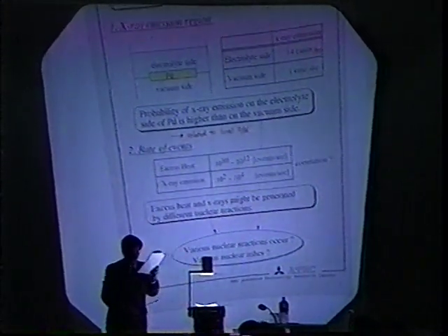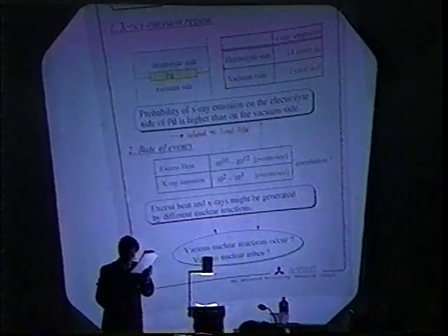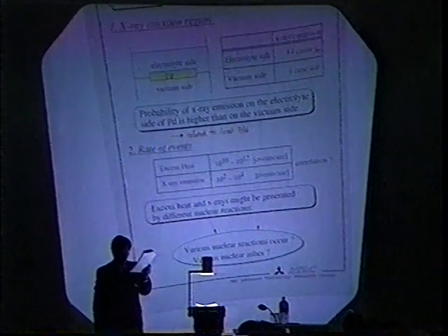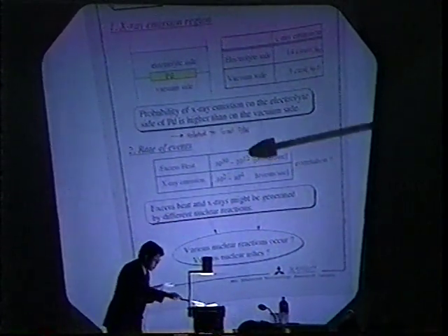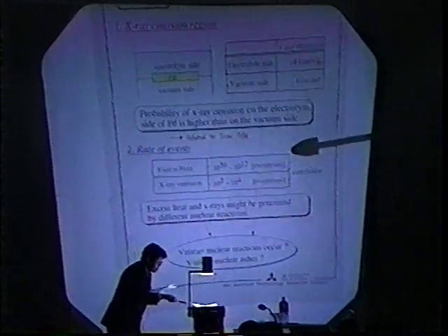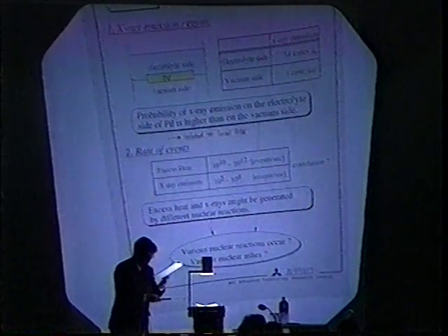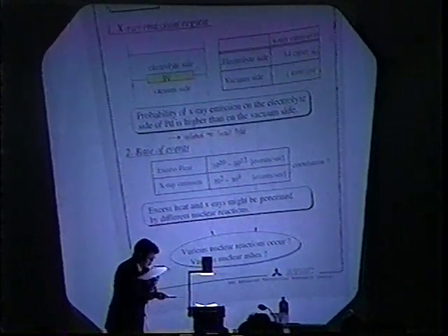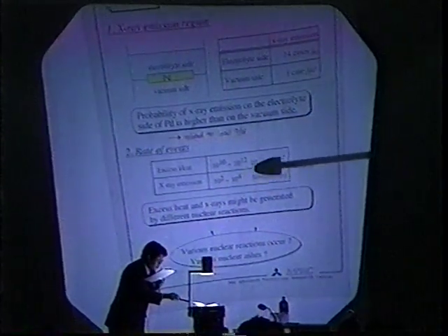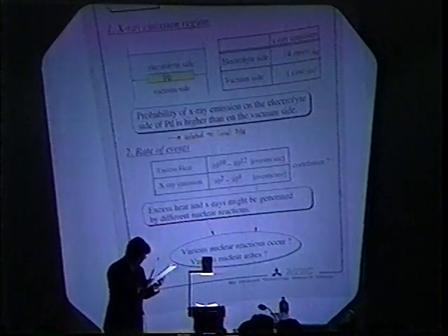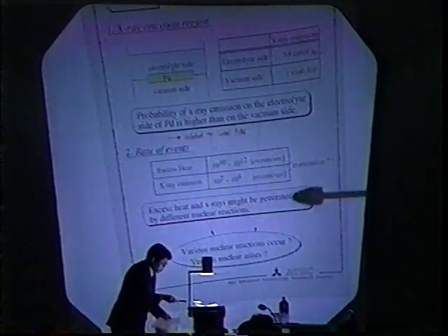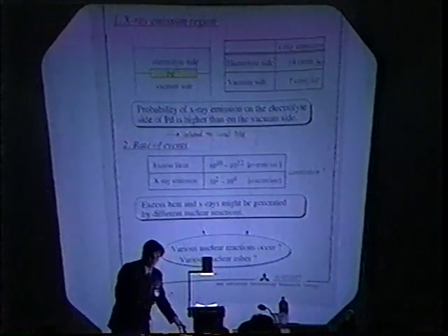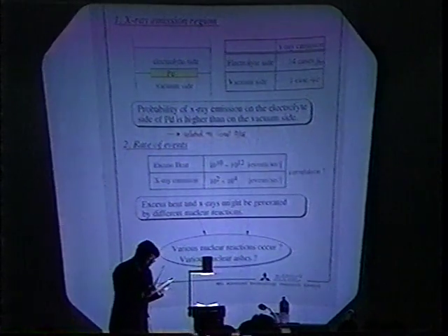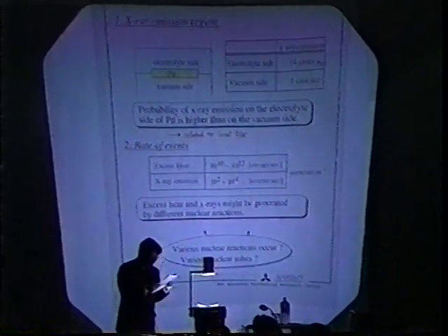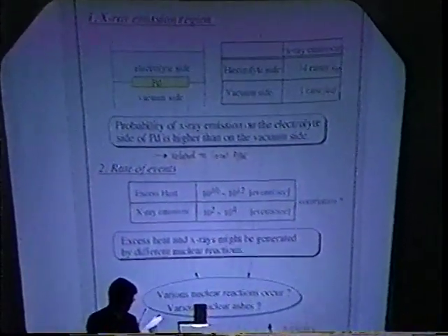Second point is the rate of events. If we assume a few MeV of energy released by one event, the value of excess heat we obtain corresponds to 10^10 to 10^12 events per second. X-ray emission calculated by Americium radioisotope ranges from 10^2 to 10^4 events per second. So excess heat and X-rays might be generated by different nuclear reactions. Perhaps I should not exclude the possibility that various nuclear reactions occur and produce various nuclear ashes.